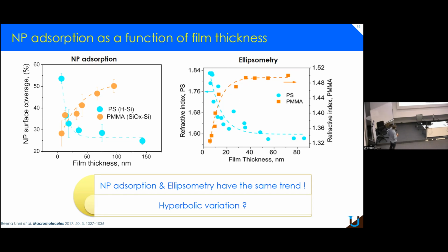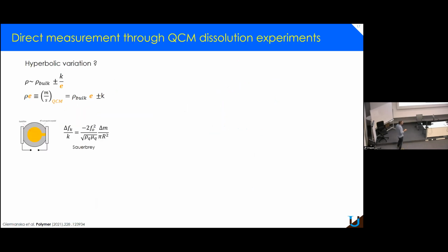So both results did agree, but again, when we tried to publish, it took us a lot of time. People were not happy at all. I remember a guy that told us one sentence: "I don't believe it." Okay, but at the end we were able to publish it, but it was still not satisfactory. So we decided to think about the system to prove that the density was directly increased or decreased with the thickness. So as you can see here, the dashed curve could be a hyperbolic variation of the refractive index as a function of the thickness. So this was our main hypothesis.